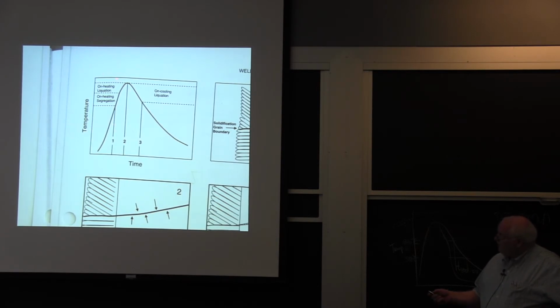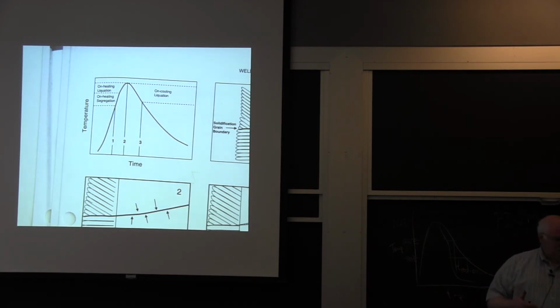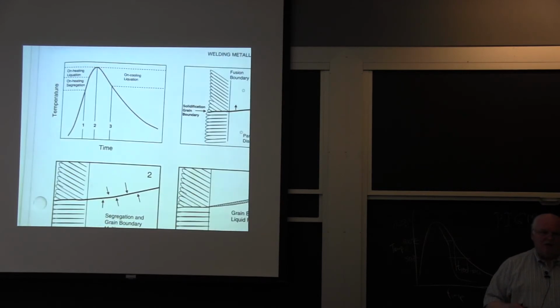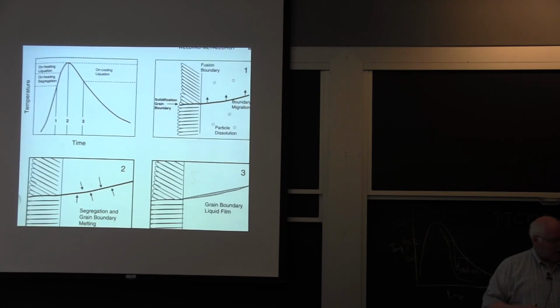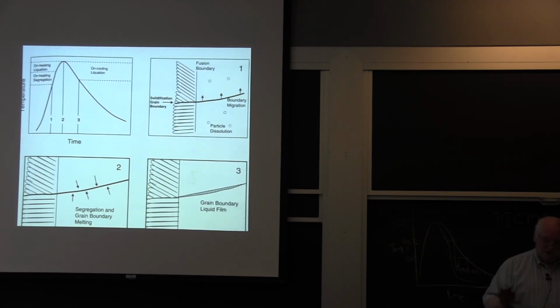So here's your welding temperature time curve, and you have liquation when you get up in the heat affected zone in particular. It's not a uniform structure. You have segregation in the metal when you melt it and reform it. But even in the nickel-based alloys, and this occurs in the Monels. In fact, it might have been a Monel rather than an Inconel that I was looking at the welds for Bettis.